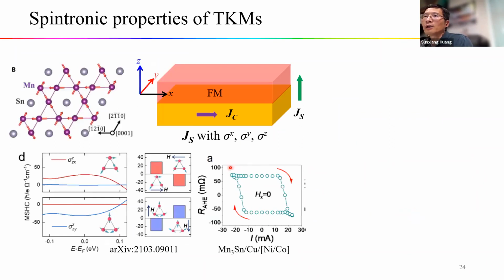Most of the audience is probably interested in this, but let me quickly go through it. Because of the special magnetic symmetry in these TKMs, one application in spintronics is that if we apply a charge current, we may realize a spin current with spin polarization along the X or Z direction, in addition to the common Y direction from the spin Hall effect. This has been demonstrated recently by a switching experiment in manganese-tin copper nickel-cobalt with perpendicular magnetic anisotropy. The basic idea is that with this spin structure, there is a Z spin polarization that gives switching without a bias field.